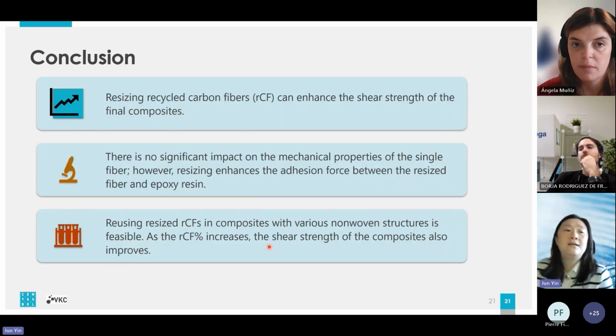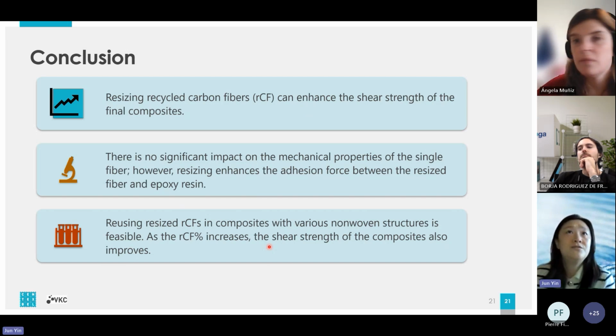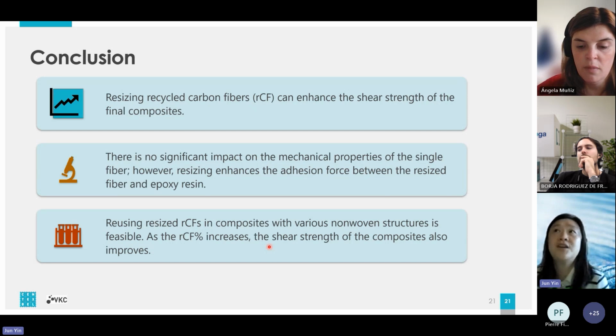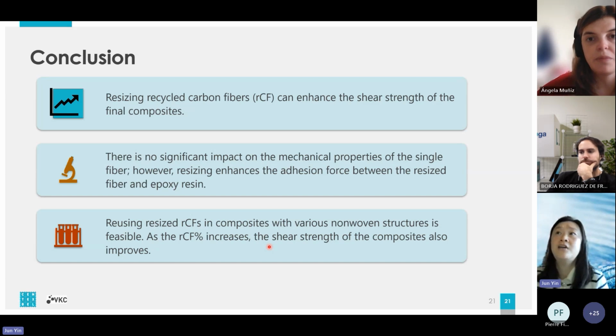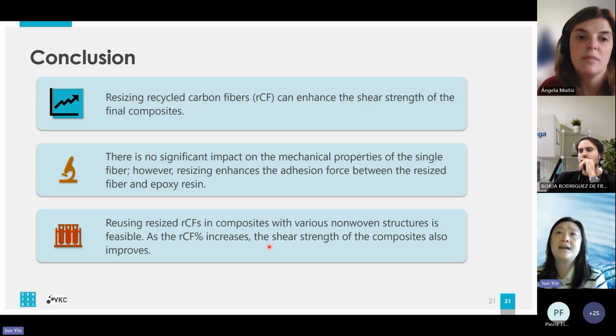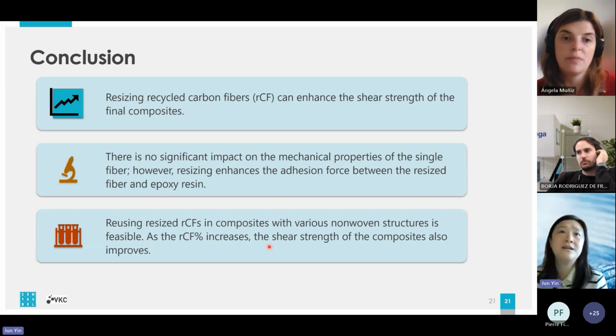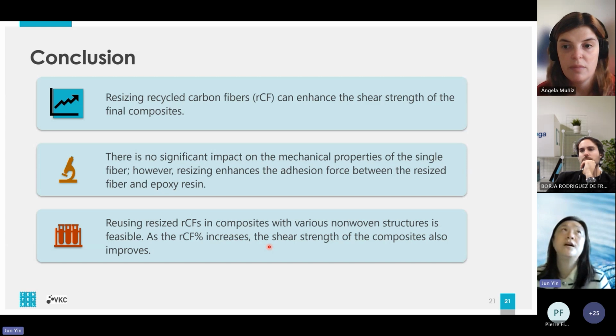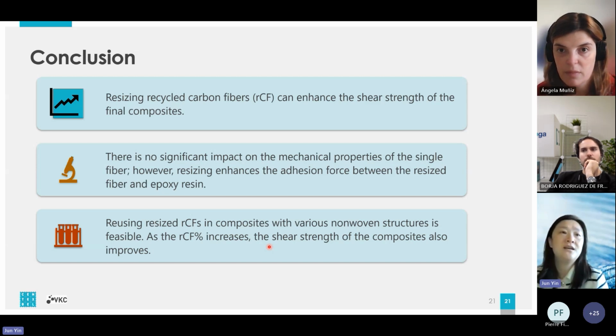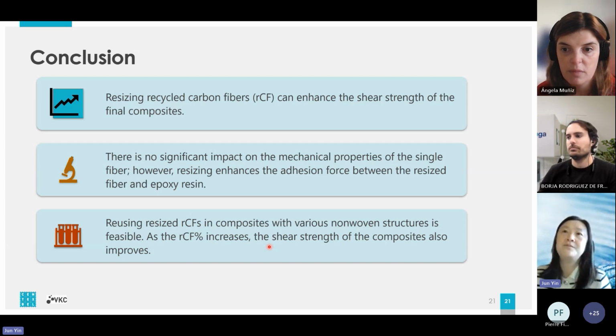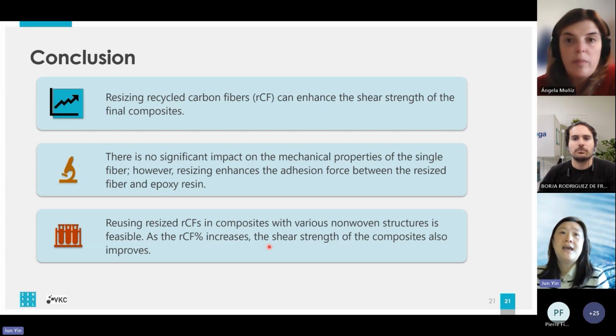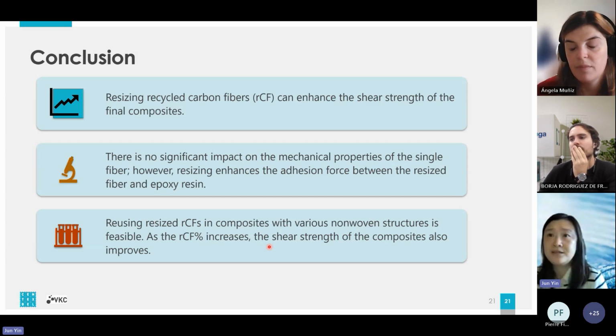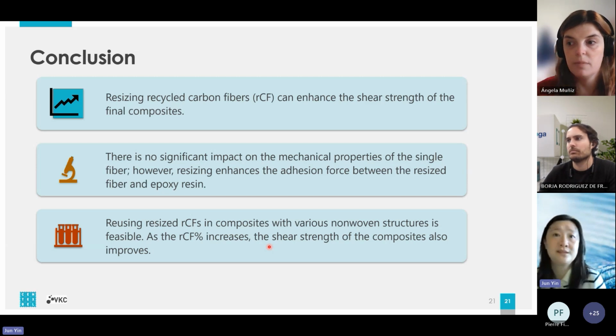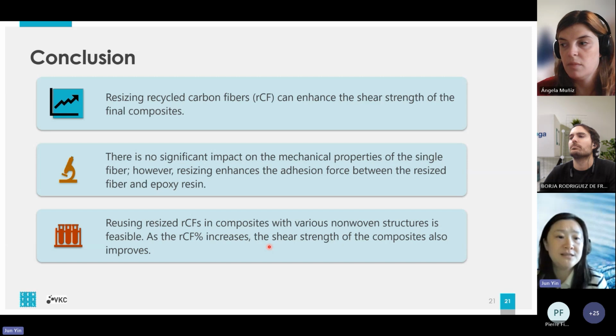So now we can come to our conclusion. The first, resizing recycled carbon fiber can enhance the shear strength of the final composite, and there's no significant impact on the mechanical property of the single fiber itself, but the sizing can enhance adhesion force between the resized fiber and epoxy. But afterwards we want to investigate by the pull-out test to really measure the adhesion force between the fiber and epoxy. And the third is reusing resized recycled carbon fiber in composite with various nonwoven structures is feasible. And with the increase of percentage of recycled carbon fiber, the shear strength of the composite improves.